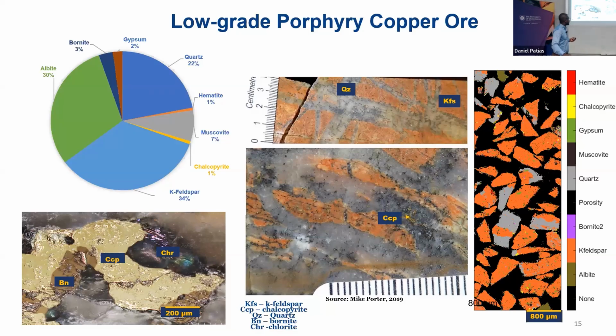In the hand material that we took, you have your chalcopyrite buried within a quartz vein, with feldspar surrounding it. We packed this material, almost 1 mm particle size, into a column, and took EPMA and mineralogical maps of it. You can see your copper sulfides as bright yellow phases, and most of it being gangue minerals, your feldspars, albite, and quartz.